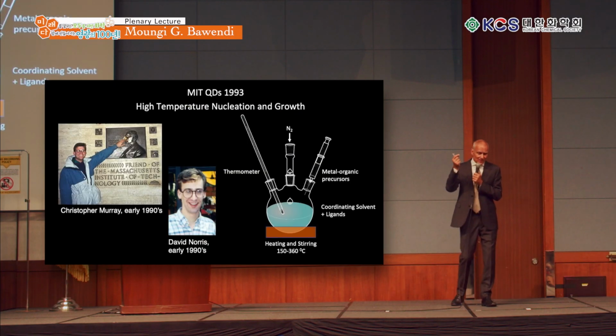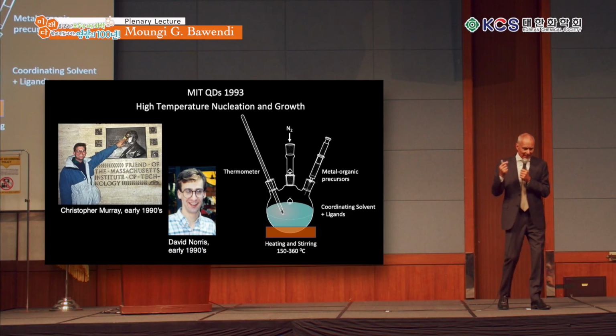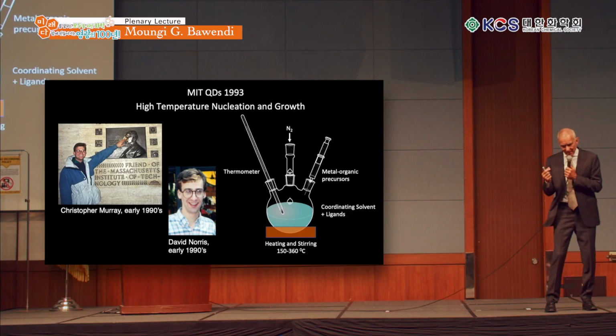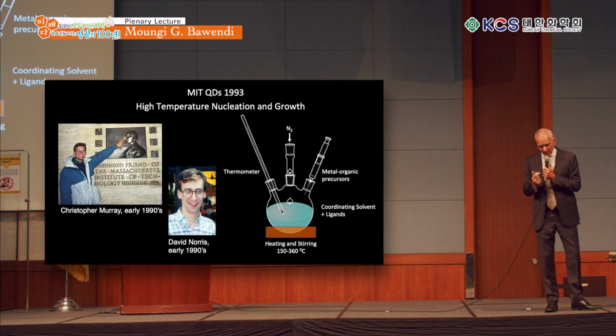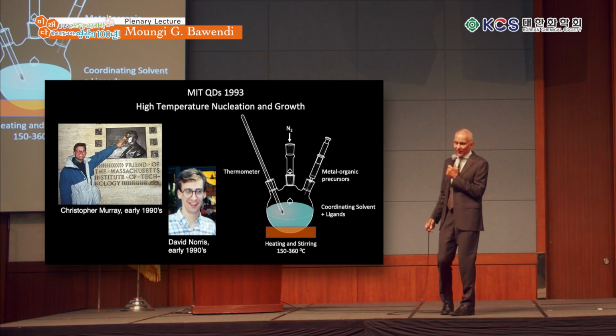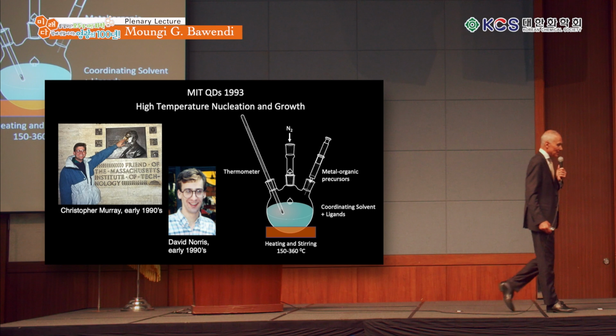So when I was at Bell Labs, I had discovered that you could take these water-based particles, which were really quite defective and not very good, and you could disperse them in a solvent, a high-temperature solvent, and make them better. And the solvent that I chose was a phosphine oxide combination. And it worked mostly some of the time, but it didn't work all the time.